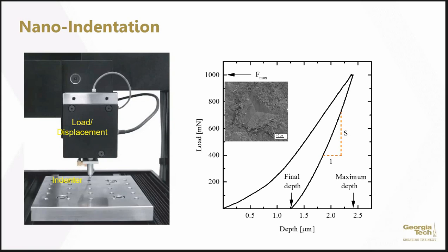The test is relatively simple. You need an indenter, which typically has a diamond tip. You can have different shapes of the diamond: semi-spherical, prismatic, or even a triangular tip. And you need a sensor that can measure the load when you make an imprint at the surface of the material. The results of a typical indentation test are shown on the right. You do the loading and monitor the deformation of the material. Then at a targeted load, you hold the load constant and allow the material to creep. That will give you information on the creep properties of the material. Then you can do unloading and monitor the elastic deformation recovery. And of course, you will have a permanent plastic deformation there, right?